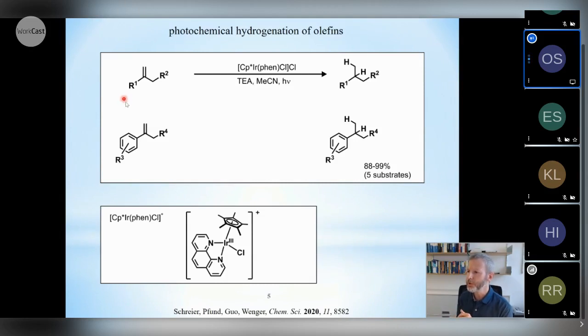And so Miriam explored a variety of different substrates, many more than five here. I only highlight the ones that worked best, and I am not going to show any substrate scope tables here because the focus of Miriam's thesis was really on mechanistic understanding. And this reaction was catalyzed with an iridium complex, which is rather well known here. This turns out to be a pre-catalyst, this iridium(III) chloro compound here.